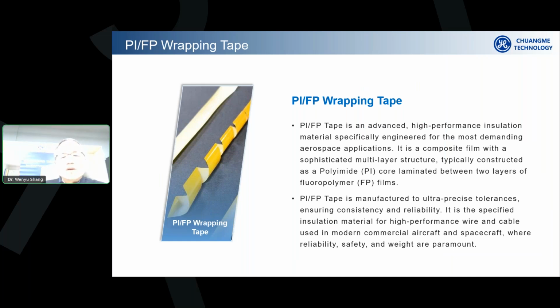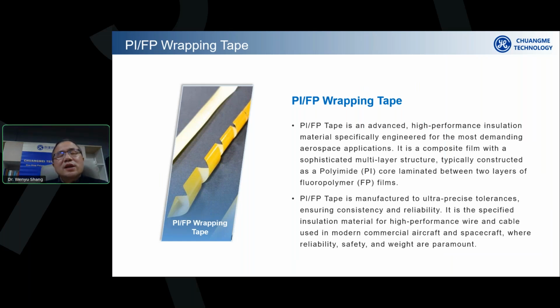It is a very smart design of this fourth generation solution, because when we take ETFE and co-extrude it on the outer layer of the cable and cross-link it with electron beam, there is a limit to it. Even when we shift from ETFE to a slightly higher temperature resistance fluorine polymer, we can increase the temperature resistance up to another 10-20 degrees C. But there is absolutely no way to increase such a technology to 250, 260, or even 280 degrees C resistance. So we had to develop a totally different polymeric insulation material to sustain such an extremely high temperature.